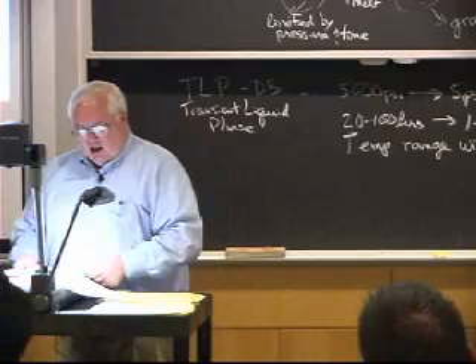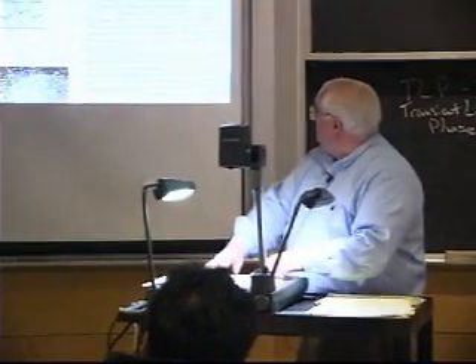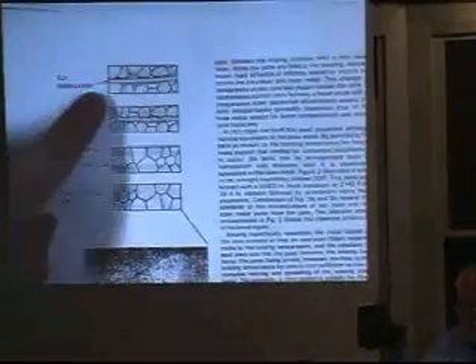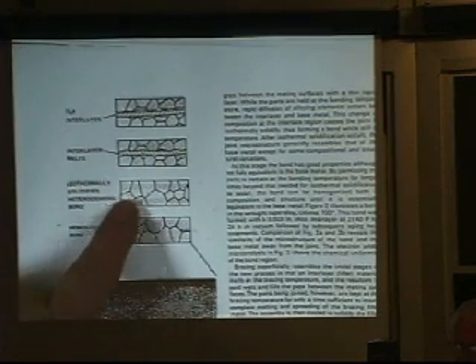Okay, you got the paper. You've got your materials with the grain boundaries, and they actually put a brazing foil in between. They show a brazing foil, but you can put powders, or you can plate the material on there, and the inner layer melts. The inner layer has to have something we call a melting point depressant. For nickel-based superalloys, the useful melting point depressant is typically boron. Boron lowers the melting point of nickel by like 400 or 500 degrees.